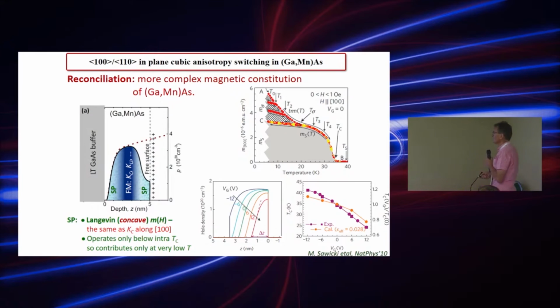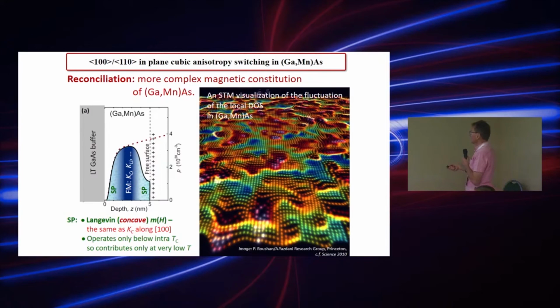And these superparamagnetic-like properties were proved to stay in this material. For example, it has been shown by electrical gating that we can change the relative concentration between this superparamagnetic and ferromagnetic component, and a change of the Curie temperature was also observed. Another confirmation of this superparamagnetism comes from scanning tunneling microscopy, where the surface of gallium manganese arsenide can be visualized with atomic precision.